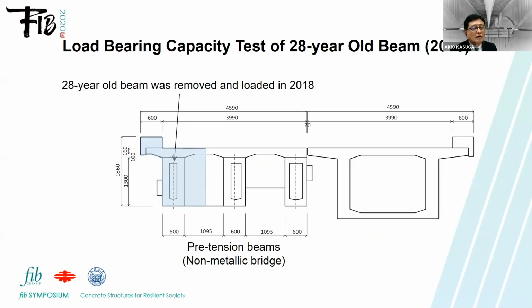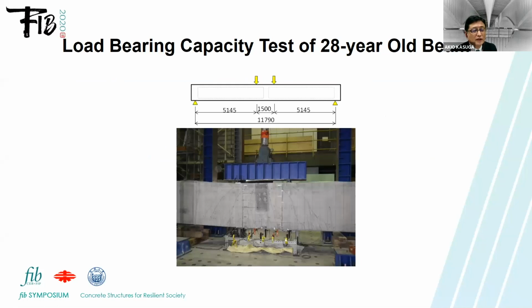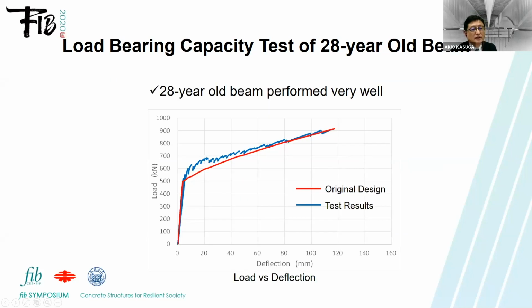So after the stories, in 2018, we cut one of the pretension beams, left-hand side, this one. This is 28 years old. And also we confirmed the strength of this short beam in our laboratories. It's a very, very simple bending test. And we confirmed that compared with the original design, the test results is almost the same, even it is 28 years old.